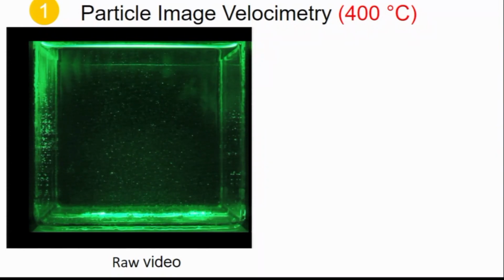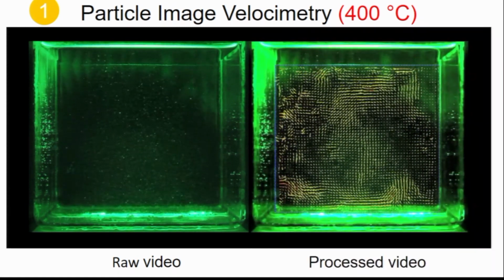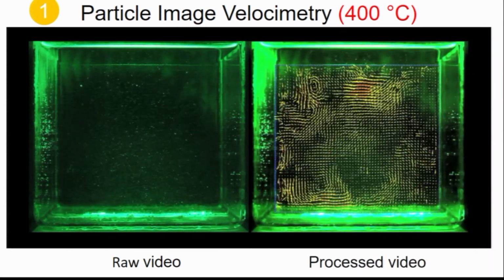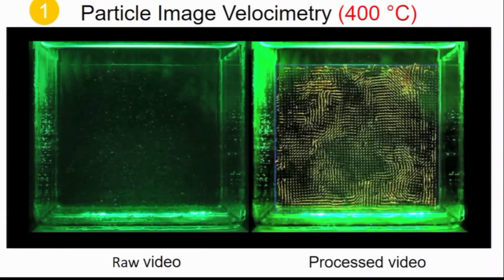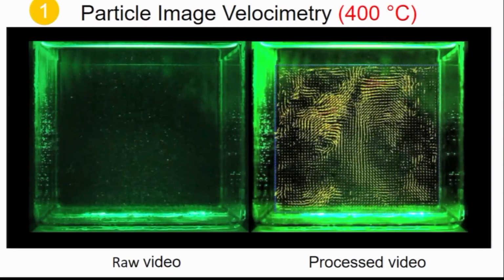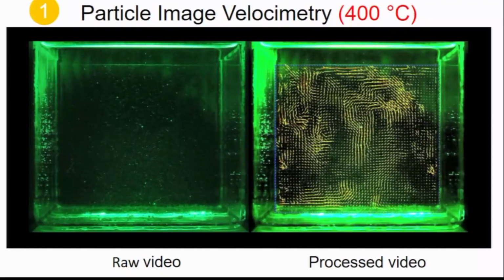So what you see here on the left is my raw video. These are little light scattering particles that the salt has been seeded with in order to perform the PIV analysis. And once again, these particles are moving only due to the temperature difference between the hot bottom of my crucible and the colder exposed surface. And then after having applied a processing software, I get my final PIV video, where what you see is the velocity vectors of every point in the salt in real time.